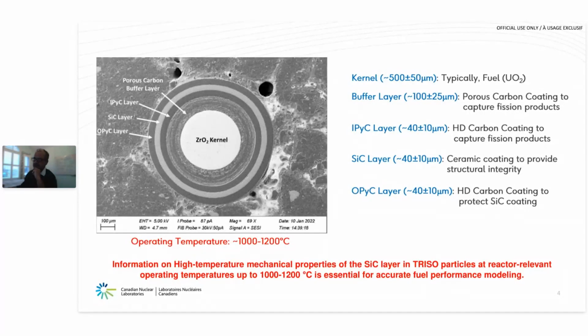On the top of this inner pyrolytic carbon layer, or the high density carbon layer, there is silicon carbide coating, which is there to basically provide the structural integrity to this entire component. And the coating thickness is also about 40 microns plus minus 10 microns. And the final coating on this particle is again high density carbon coating called outer pyrolytic carbon coating layer, which is there to protect silicon carbide layer itself.